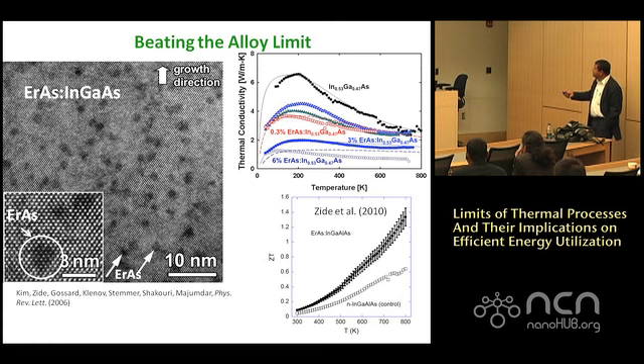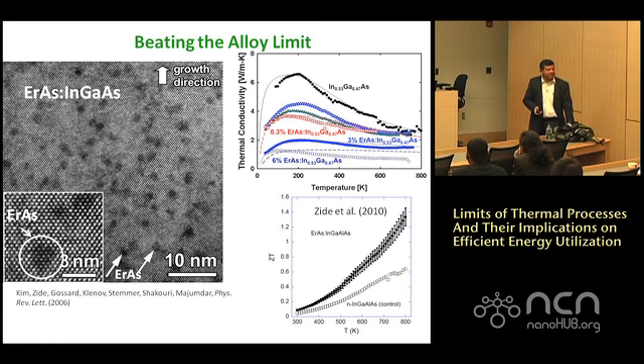And here is ZT of this material going up as a function of temperature. This is indium gallium arsenide itself. And you can cross 1, you can get 1.4 or so. But this was a model system. That is, it worked for this because we could control the material. And it happens to be a pretty good semiconductor as well. There's some other bandgap engineering that was developed for this. But nevertheless, this is not a magic thing that you can suddenly get ZT greater than 1 because you can actually design the material for it.